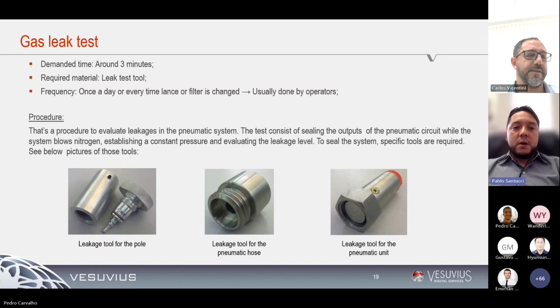Not only calibration gas, but also checking the leak of the entire system is recommended, because any kind of leak can and will influence the final readings of our system. So keeping a perfect sealing in the entire system is the best. So every time a part needs to be changed, for example, a lens or a pole or a hose inside our system, it's highly recommended that a leak test be put in place so that once again we can guarantee there's no leak being built after this swap.